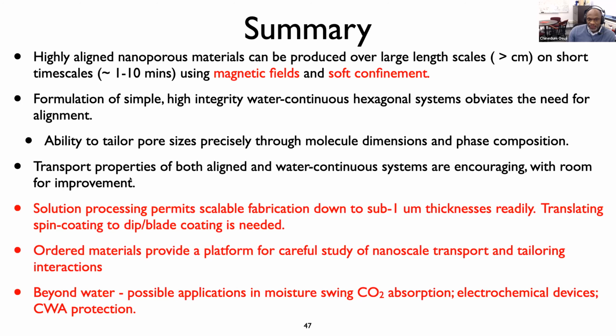We've been able to see attractive transport properties in both aligned systems, as I did not talk about, but also water continuous systems. And these transport properties are encouraging, and there's certainly lots of room for improvement. I think the contribution really rests on the fact that we can now make these membranes using solution-based processing routes. And so that permits scalable fabrication. And we're looking at membranes down at a couple hundred nanometers of thickness with pore sizes that are sub 1 nanometer and variable by units of probably 0.1 or 0.2 nanometers.